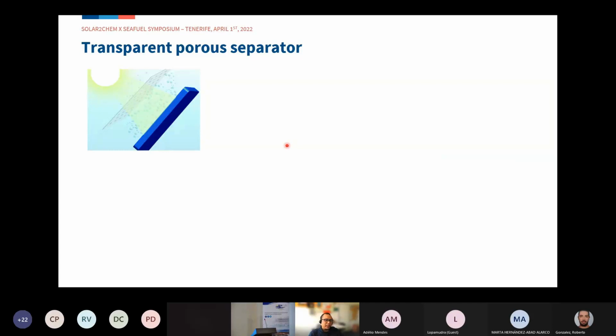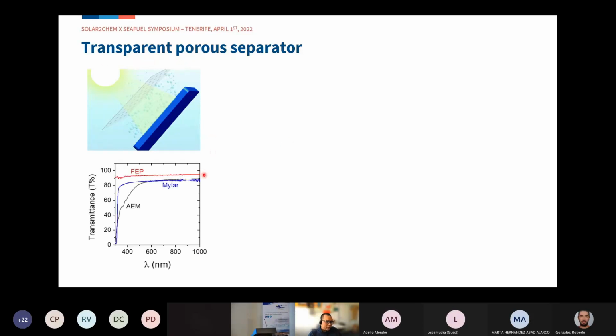Some designs that are out there require that the illumination pathway have the membrane or separator placed in the illumination pathway. If that is the case, we actually need to have transparent separators. This is why we then tried to look at several polymer sheets, for example FEP and Mylar, and see whether we can make use of them, introduce porosity, and see how it performs as a separator.